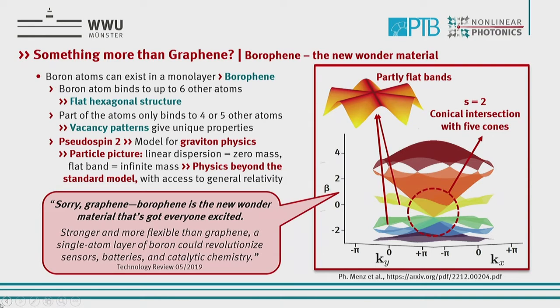But what we found is that when you excite these structures here at this area of this 5 intersection, you really get a pseudospin of 2. And also, you can distribute the different features and see the degeneracy of these 5 cones and access them with different phase structures.